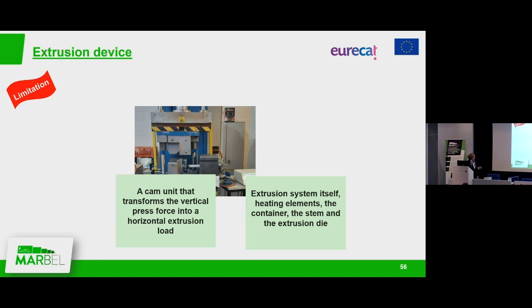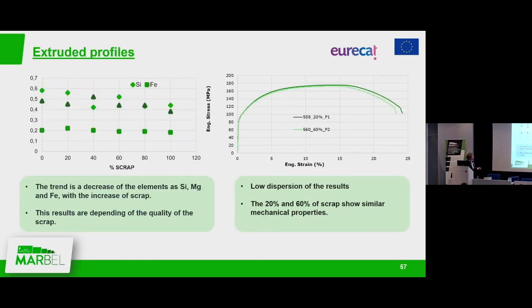With this special tooling, we are able to produce aluminum profiles and evaluate them. The most important for us is the extrudability, because we need to know what happens if we increase the scrap, what happens if we increase, for example, iron, because we find these elements in the scrap, and we evaluate the extrudability with this special device. I'm not going to go deep into this graph, I only want to show you that we evaluate, as I told you before, the elements that we found when we increase the scrap, and with tensile tests we evaluate the mechanical properties. Our focus was to increase the scrap content by more than 50%. Here we found that in the case of 20 and 60% of scrap, the behavior is similar. For this reason, we translate this knowledge to produce the profiles at industrial scale.